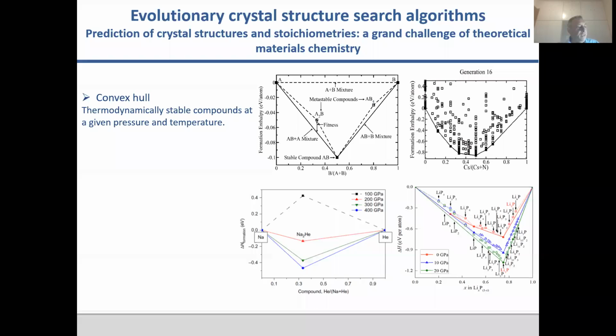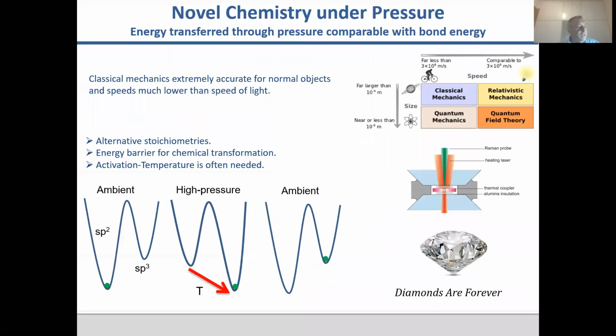It looks like the periodic table, or the rules that we know, are not valid anymore, at least not to the extent that they are at ambient conditions. And the reason is that the energy we transfer through pressure to the system is comparable with the bond energy. So in reality we change the energy landscape. Usually, when I give this talk to a general audience, I try to make the parallel with classical mechanics, which is okay for normal conditions. But then when you start to apply classical mechanics to things like large objects and so on, you need new theories. So this is why we can access novel stoichiometries, because we change the bonding.